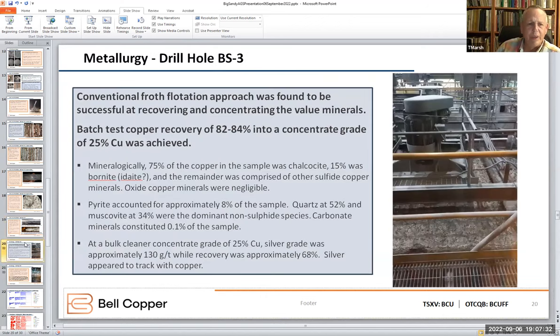Now, I always knew if I ever got something resembling ore in a core sample, I was going to get it in and make sure it would come out easily. So we sent the assayed interval from BS3 into SGS Lakefield up in Ontario and had froth flotation and acid leach testing done on the chalcocite. Turns out it does pretty good. We recovered 80% of the copper into a concentrate grading 25% copper and 160 grams of silver. So that worked pretty good.